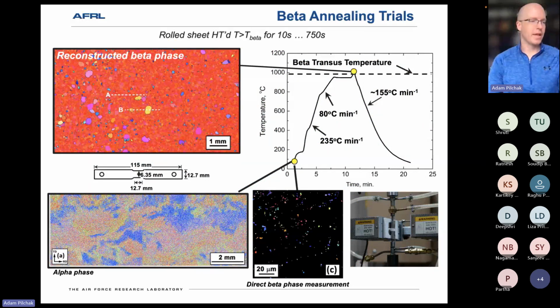And so in that original work looking at the rolled plate material, we had basically characterized all of these intermediate annealing steps, but because they weren't fully recrystallized, we put all of it back in the drawer. The data just sat on a hard drive for several years, and we thought it was a failed experiment basically, because we didn't get the microstructure that we wanted for the remainder of the investigation. But after seeing similar features on the structural forgings, we dusted off all of the old data and all the old samples, and started looking at it again.